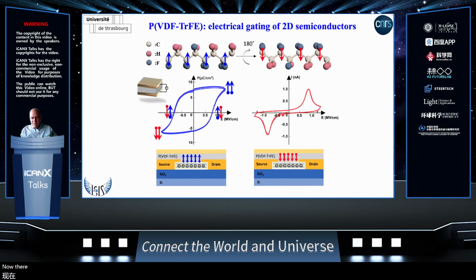Now, the first thing we did was to integrate a 500 nanometer thick layer of this ferroelectric material on top of the tungsten diselenide in a capacitor type of device, and we performed 10 cycles. We can see that there is an absence of any fatigue. Essentially, we are switching from dipole up to dipole down.